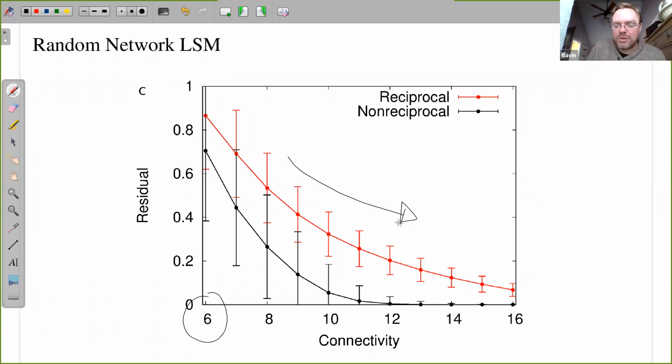One trick that I started doing is this: a spring is reciprocal, right? If you pull a spring, then every action has an equal and opposite reaction. You have the same force on both ends of that spring. But in terms of mapping this on, there's really no reason to assume that, because we're just building this model out of these pairwise interactions to make it as easy as we can. It doesn't make it any more difficult to have different spring constants from either end. So I've introduced a non-reciprocal spring.